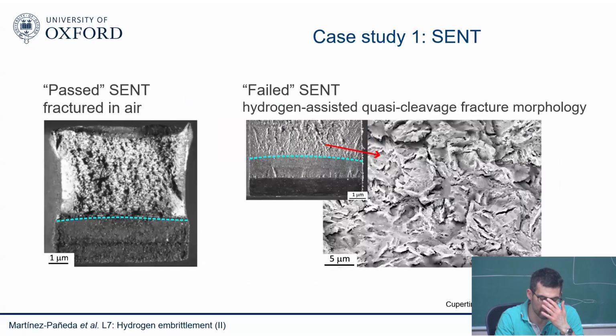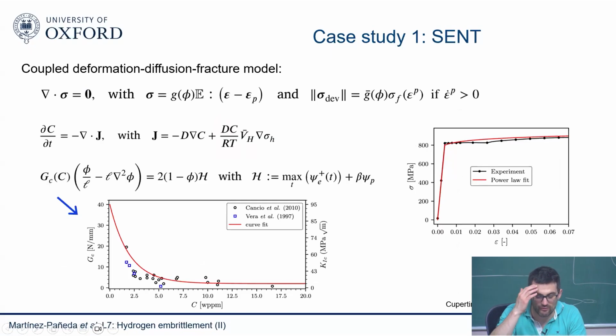And then what you see, well, you need to see if your SENT passed or not passed. So a case that will pass, you have a ductile fracture. One that failed, you see quasi-cleavage fracture morphology. So this is not a component that you want to put in service, basically. That's the idea. And then the phase field model is very similar to the ones we discussed before.